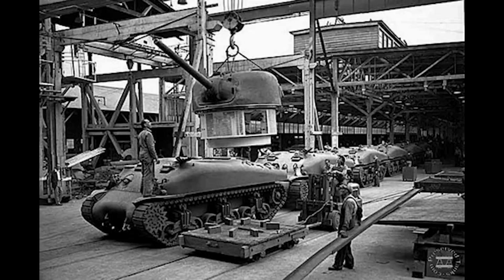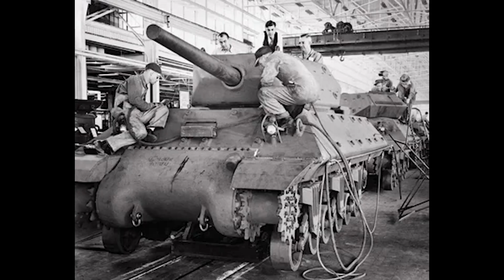These heat treatment processes were critical. Too hard, and the armor would shatter under impact, sending deadly spall fragments into the tank's interior. Too soft, and shells would penetrate more easily. American metallurgists had spent years determining the optimal hardness levels for different armor thicknesses. For armor plate less than 32 mm thick, American specifications called for Brinell hardness numbers of 302 to 325. For thicker plates between 76 and 127 mm, the specification was 240 to 260. The thickest plates, over 127 mm, were tempered to 220 Brinell hardness.